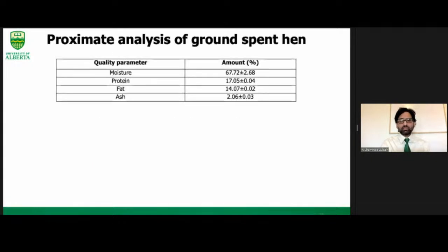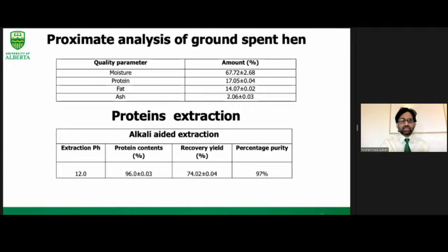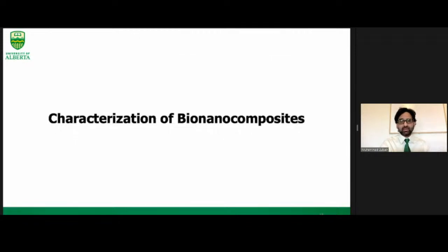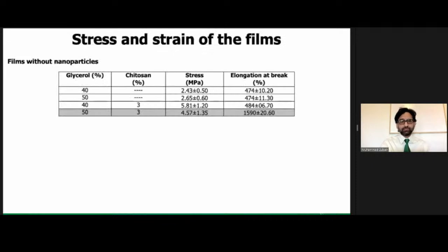The proximate analysis of the ground spent hen showed that the moisture content was around 67%, while the protein content is 17%, as I already discussed. For the proteins extracted using this method, the recovery yield was around 74% and the percentage purity was 97%. After the successful extraction of these proteins, they were further characterized using different techniques. The first thing that we studied is the stress and strain of the films. These are the films developed from proteins without addition of any nanoparticles.